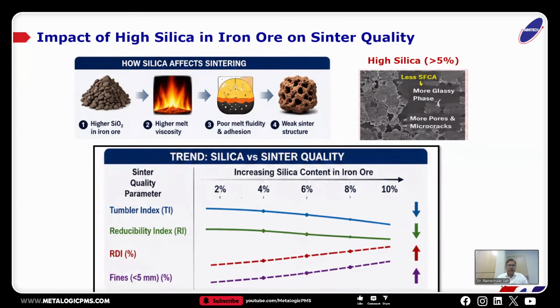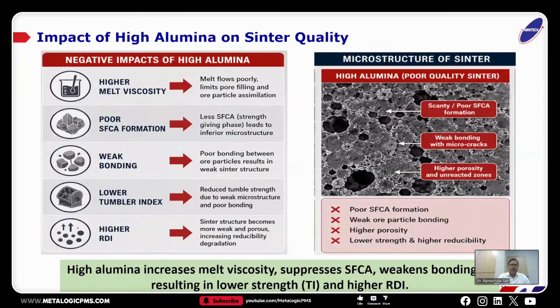Looking at the trend, beyond 4% silica the quality of the sinter product becomes poorer. It reduces the strength properties as well as the reducibility. The effect of alumina is similar; rather, I would say it is a bigger problem than silica for the sinter makers. Because alumina being a refractory mass has a higher melting point, it increases the melt viscosity. It is a stumbling block for SFCA formation, which is the strong bonding phase. It makes your bonding poor, and ultimately you land up with a very poor quality of sinter.